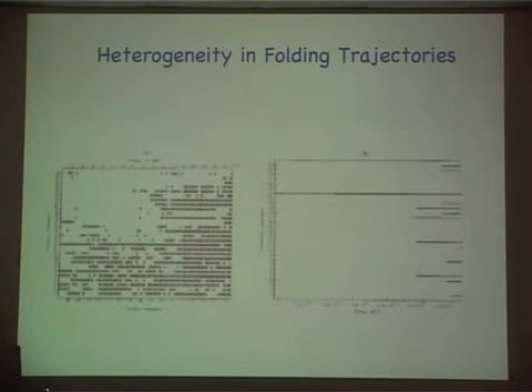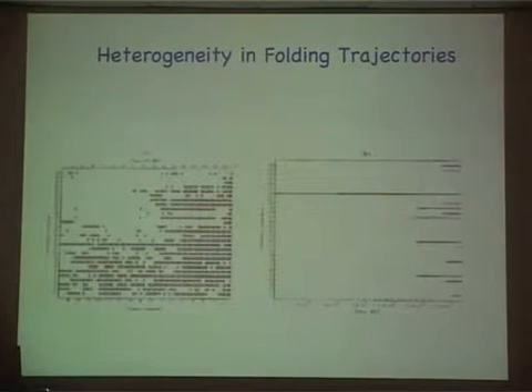So we created these. This is a horrible picture, and it does not even correspond to the Brownian dynamics simulations of the two structures that I showed you in the previous slide. It's a lattice model. The only point I want to make is the following. These are two different folding trajectories created for this lattice model, in which you go to high temperatures, and presumably they're unfolded, but you know everything about this system. And then you run the simulation until it reaches the folded state for the first time. So that's the left-hand trajectory, and this is another, independent one. And by eye, you can tell that these two trajectories are very, very different.